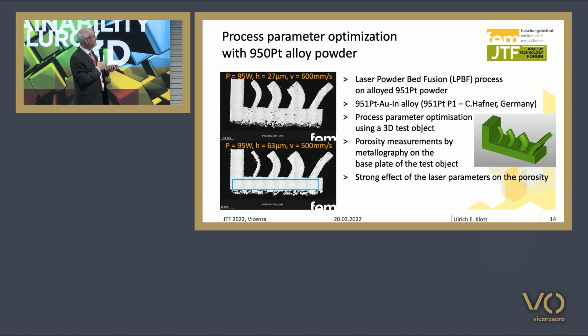It's a commercial alloy powder, platinum gold indium alloy by C. Hafner in Germany. From this alloy, we built little test parts. These are a wedge type sample with some wires of different thickness.